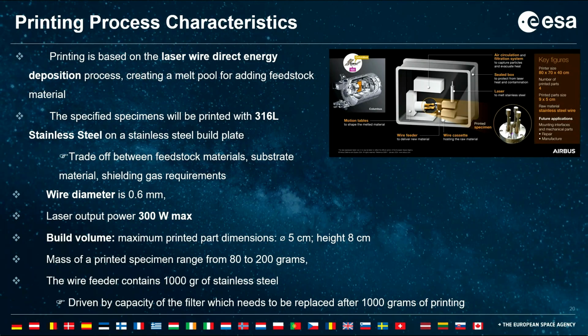The wire diameter is 600 micron, 0.6 millimeter. Laser output power 300 watt. It's also dictated by the safety requirements on the ISS. It's quite a small build volume, 8 centimeter high by 5 centimeter diameter, but it's good enough for the demonstration that we wanted to do. Typical printed part is 80 to 200 grams. And the wire feeder, we have the cassette with the wire feeder, contains 1,000 grams of stainless steel.